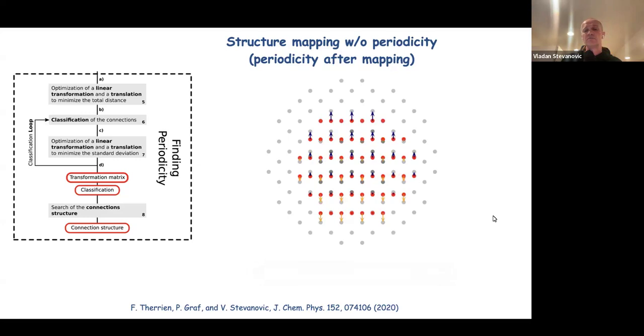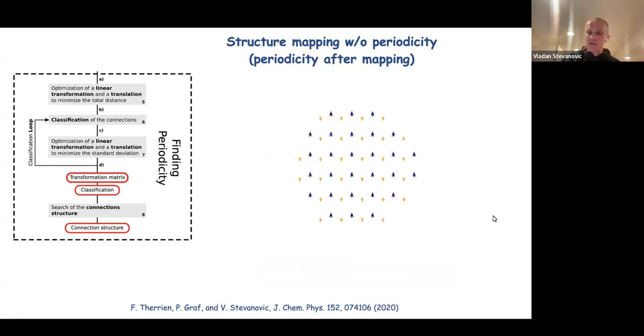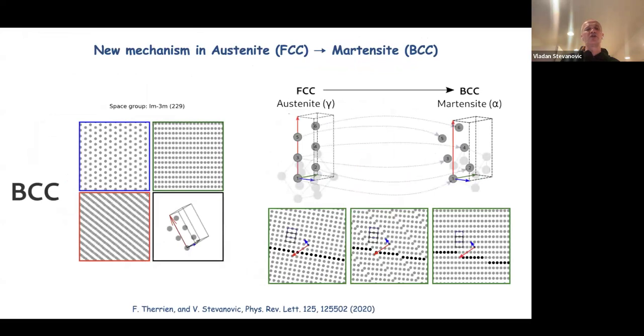So this will produce, depending on the sizes of these spheres, different results. And for the most part, for those prototypical transformation mechanisms that people were discussing before, we produce results that are either exactly the same or very similar to what people have found, with one notable exception, and that's the actual martensitic transformation in martensitic steels. So this is the famous FCC to BCC or austenite to martensite phase transformation. And in the left panel, I will show you what you get if you try to minimize the total displacements of atoms without periodicity and then recover periodicity after the fact. So I will play you a little movie